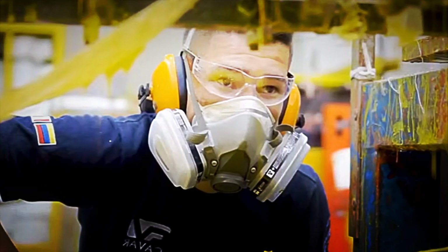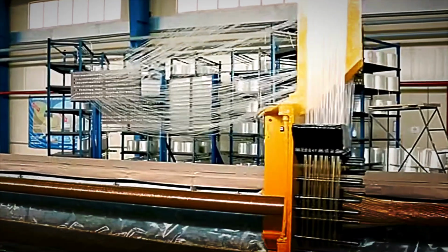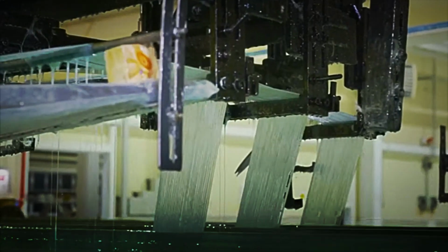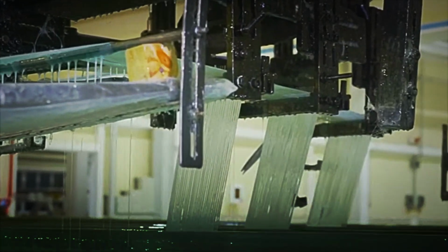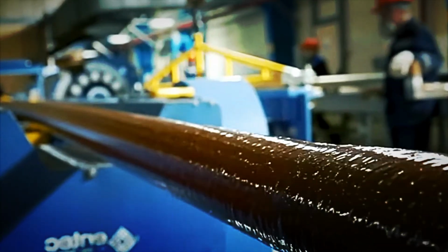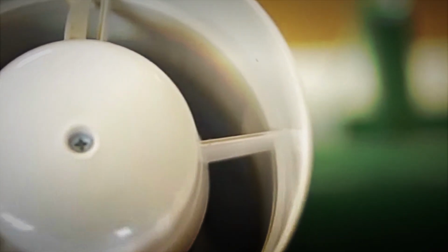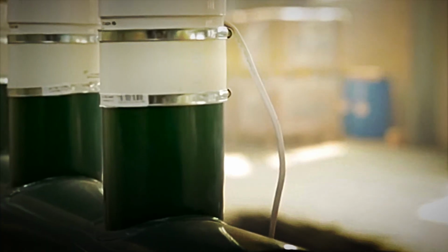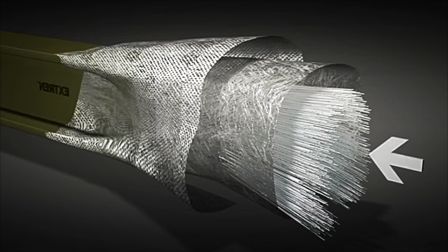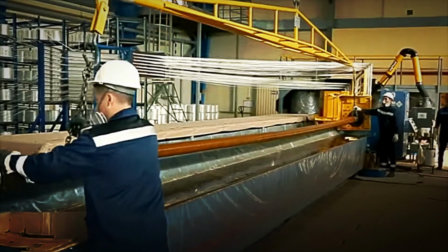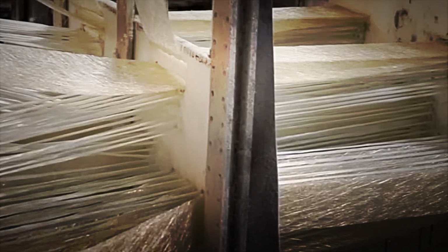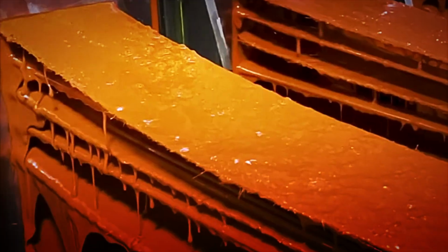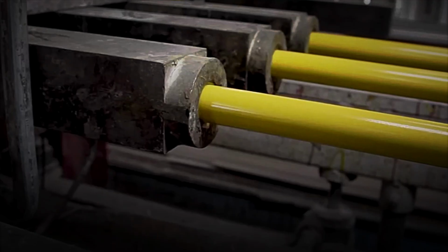Typical tension values are maintained within a range of 5 to 30 newtons per filament, although this parameter may vary depending on the specific product design, the type of fiber used, and the line speed. Automated control systems continuously compare the measured values with the established parameters. When a deviation beyond the tolerance limits is detected, the system issues visual and audible alerts that allow the operator to make corrective adjustments without needing to stop production. In some cases, more advanced systems make automatic corrections through servo motors that adjust braking pressure in real time.